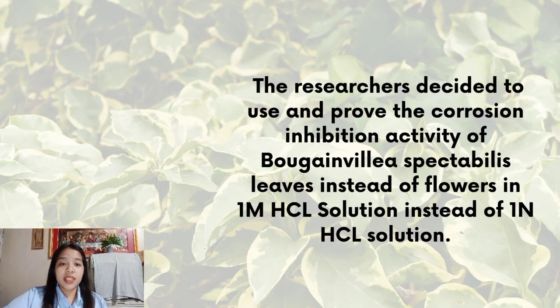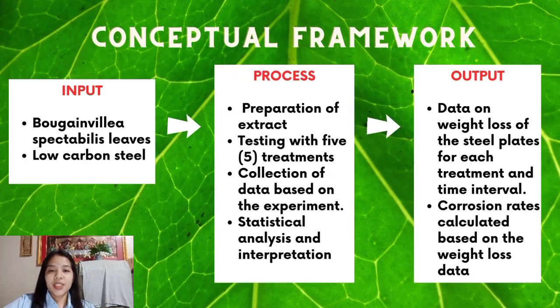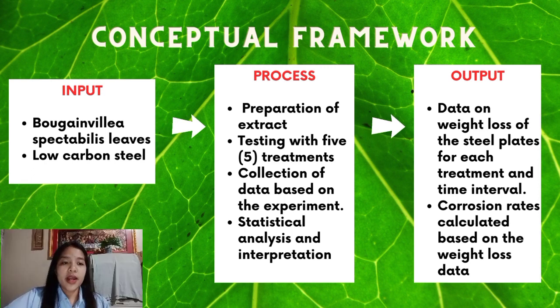With all those things having been said, the researchers decided to use and prove the corrosion inhibition activity of Bougainvillea spectabilis leaves instead of flowers, in 1 molar solution instead of 1 normal hydrochloric solution. The experiments commenced with the preparation of Bougainvillea spectabilis extract, which was air-dried, pulverized, soaked in ethanol, and rotary evaporated. 1 molar hydrochloric acid solution was used throughout this study.